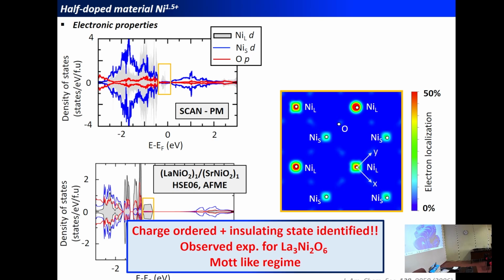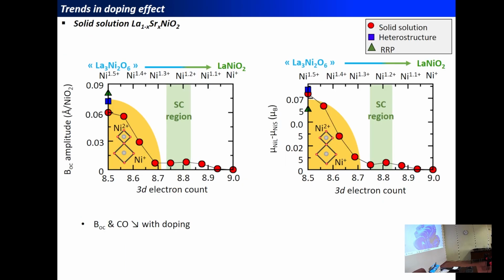In terms of the infinite layered phase with the solid solution, it might be difficult to synthesize the half-doped solution due to the miscibility limit between strontium and lanthanum. Nevertheless, if such a solid solution could be feasible, we should expect to have this type of charge ordering in the system. And therefore, we can now continue to analyze the electron doping effect starting from this charge-ordered insulating state, which is very similar to what we get in bismuthate. Since the 3 starting points, the reduced Ruddlesden-Popper heterostructure or solid solutions, give the same results, we just decided to focus on a solid solution, which is much easier for us to perform in the simulation.